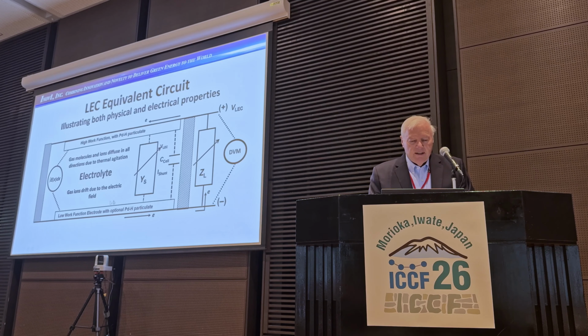So the electrolyte here, what happens is the materials would like to go back to their native state. In other words, a high work function electrode has more electrons than it likes. Low work function electrode is looking for electrons. So we've got to transfer electrons from the high work function to the low work function. There's an electric field in here, and we're actually transferring electrons against the electric field. And that's one of the reasons why in the curve you saw for the power, there's kind of a midpoint in between. And that's where the maximum power is produced.